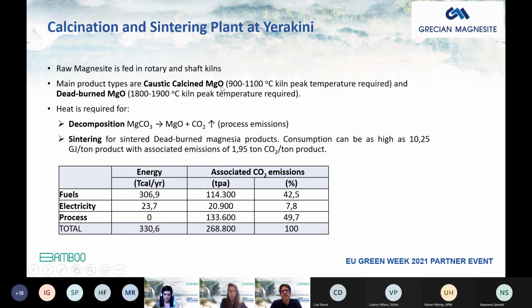The main difference is that caustic calcined MgO is a product that still has chemical reactivity and is thermally treated at relatively low temperatures. For example, the kiln peak temperature required is around 900 to 1100 degrees Celsius, while dead burnt MgO, which is a refractory product, which has to be chemically inert, has to be processed in the kiln with a peak temperature as high as 1800 to 1900 degrees Celsius, and can also reach 2000 degrees Celsius or more in certain cases.